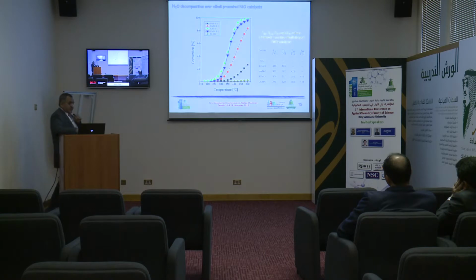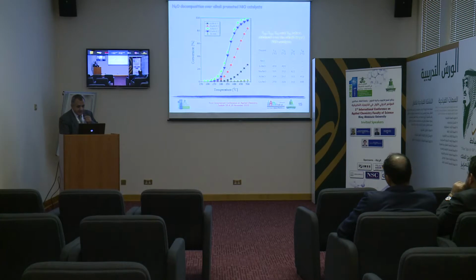Also, this table represents the T10, 25, 50, and 90 percentage, which refer to the conversion percentage. One can observe here that this T10 decreases markedly upon adding the lithium, followed by sodium, potassium, and cesium.